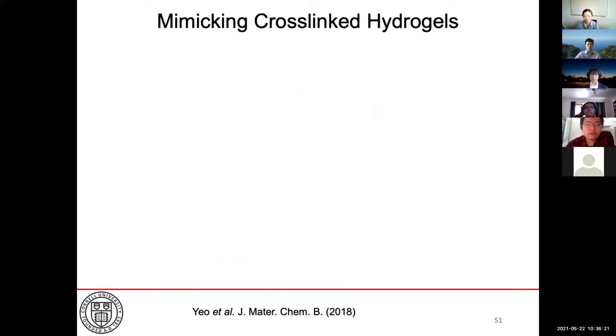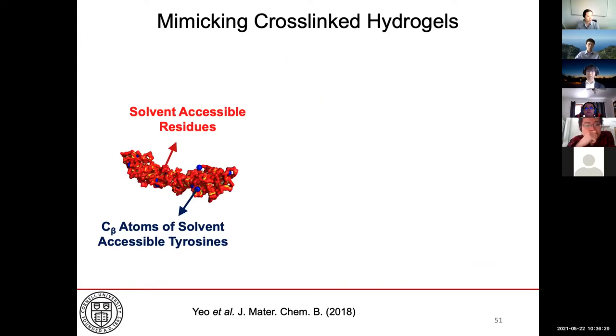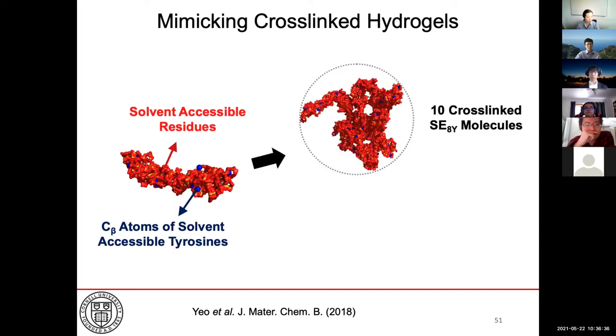And therefore, my final broad aim of constructing a coarse-grained model is to be able to explain the concentration dependence of the thermal response. So I developed an algorithm that successively locates solvent-exposed tyrosine side chains of a single silk-elastin molecule, and I cross-link two such side chains together. And this mimics both the tyrosine cross-linking that's catalyzed by horseradish peroxidase, as well as an increase in the concentration of the hydrogel. And therefore, we actually provide a representative region of the full hydrogel.